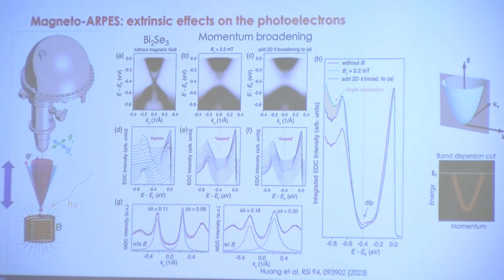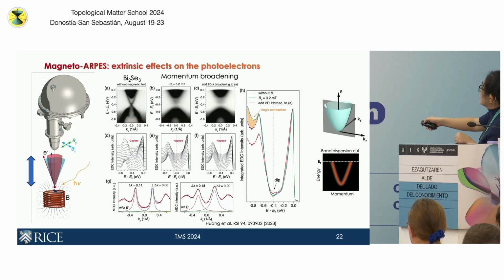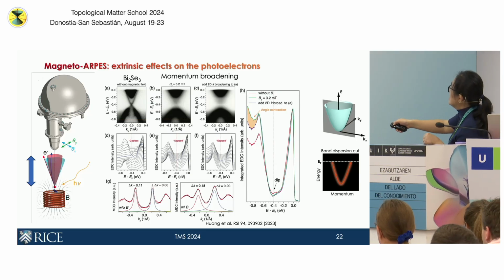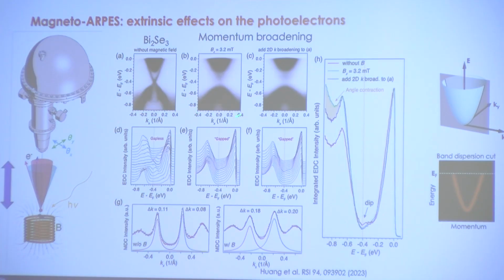And the third one, I just want to caution a little bit. We tried to look at what is the effect of magnetic field on bismuth selenide. So this is without a field, and when we first added the field, we saw the Dirac cone is gone, which is kind of interesting. But Jianwei, being the really careful guy that he is, thought deeply about why this is before jumping to conclusions. And we realized that this is actually due to a trivial momentum broadening effect. Just a word of caution for those of you who want to explore this technique.